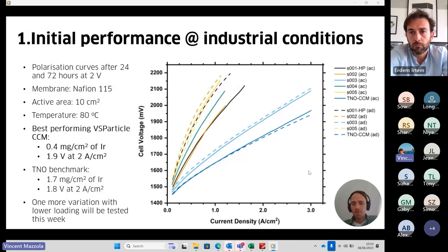So the best performing CCM at the moment is this light blue line. The dark blue line is the state-of-the-art performance. It's not our membrane. The light blue one is our best performing CCM with 0.4 milligram per square centimeter of iridium, which is much, much lower than the dark blue one. If you want to know more information about performance, feel free to always contact us.